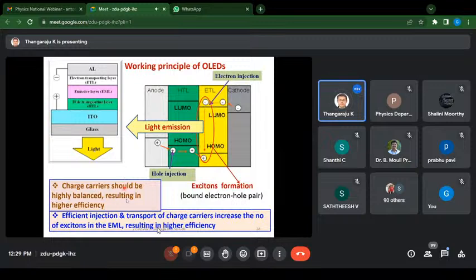to characterize the devices. So there are different parameters to be optimized. Charge balancing is important: charge should be injected in a balanced way, and various parameters such as thickness and the work function of the electrode are very important to make balanced charge carriers in the organic light emitting diodes. And to give higher device efficiency, more excitons should be formed, so the internal quantum efficiency should be 100%. In the case of organic semiconducting material, the internal quantum efficiency is achieved to be 100%, whereas the external quantum efficiency is still not achieved to the highest level. So the work is still going on to improve the external quantum efficiency in the devices.